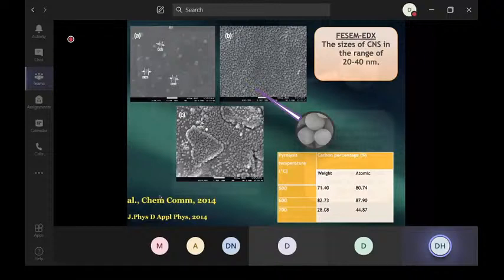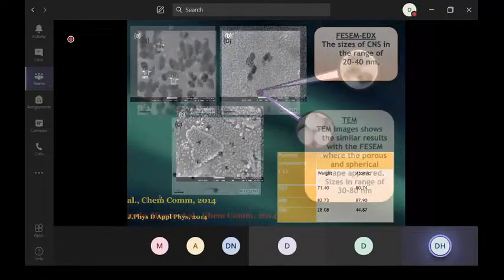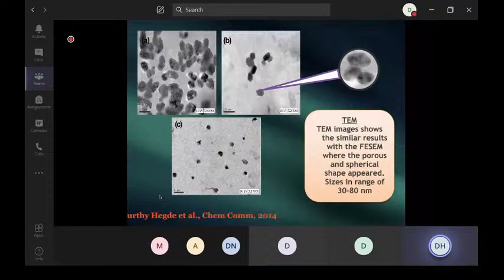Then we subjected it again to the transmission electron microscope just to prove whether the material is porous or not. Here you can see there are a lot of layers. There are very smooth layers you can see here, which is porous and spherical. So TEM says that the material you made is spherical and also porous in nature, like graphitic layers. You can also see a porous structure present in such kind of materials. So this is another one.